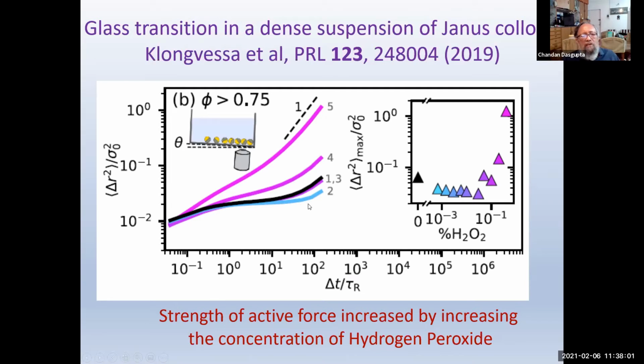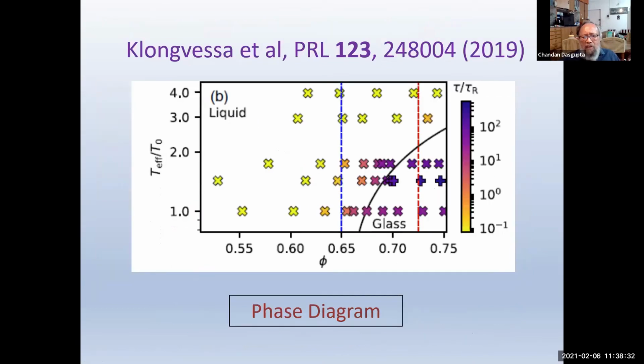At the bottom, the mean square displacement basically becomes a plateau. So that is either a very sluggish liquid or it could be a glass. But then as you increase the strength of self-propulsion, eventually at long times you get diffusive behavior. So this is an experimental example of a glass being melted because the strength of the activity is increased. This is a sort of artificial active matter, but the same phenomenology can be seen here also.